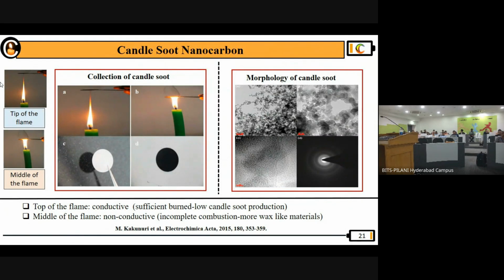So what is this candle soot? As I said, you just have the candle, burn it, and collect the soot, and then that's how you deposit the candle soot on any substrate. When we look at this candle soot in microscopy, FESEM or TEM, what we see is a fine interconnected network of carbon nanoparticles, which are around 40 to 50 nanometers in size. Of course, it depends on where you collect the soot, whether from the tip of the flame or the middle of the flame. It gives different kinds of soot particles, because in the middle of the flame there is incomplete combustion of wax, and there are a lot of impurities present, and that becomes non-conducting.